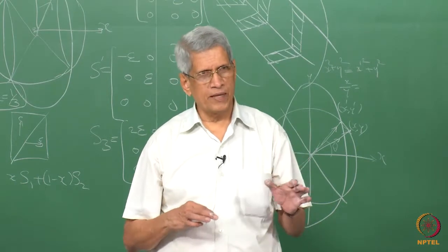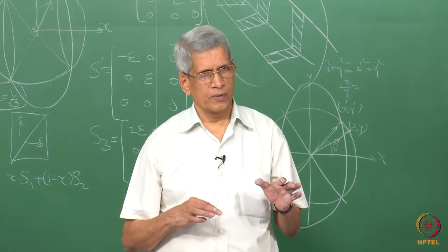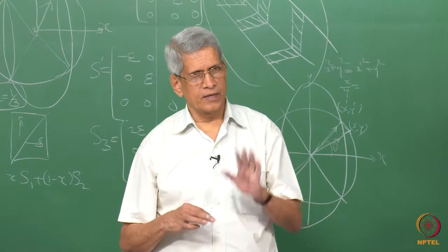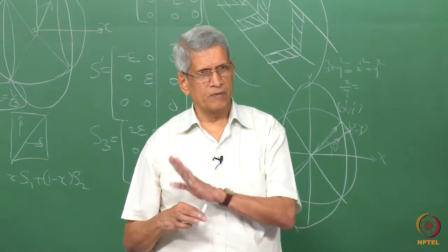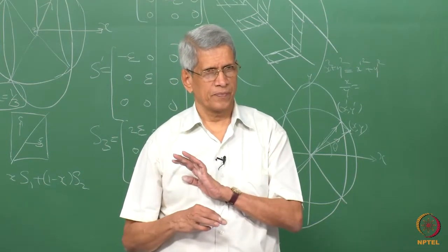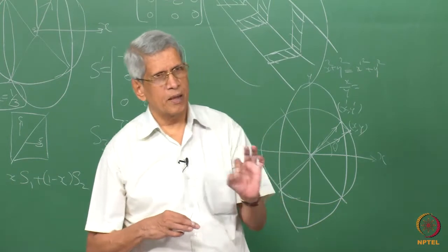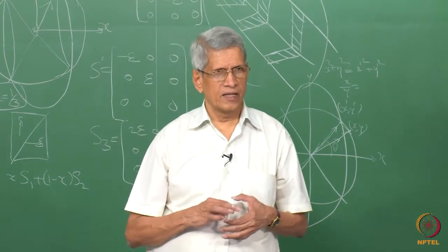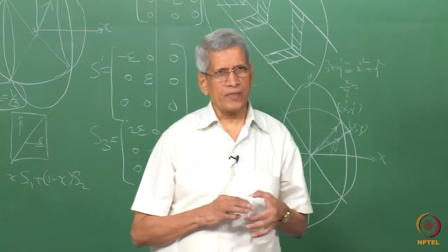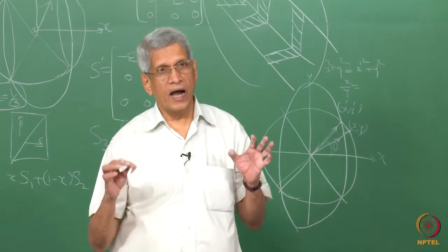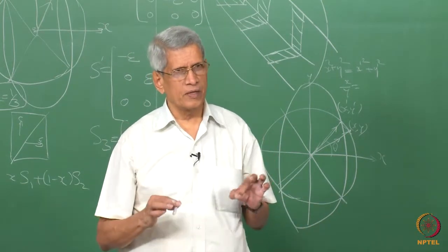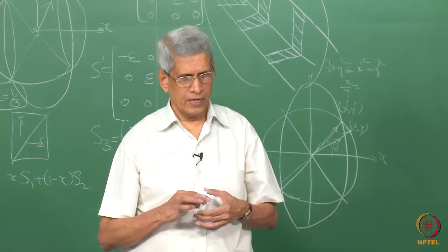Then the habit plane which is calculated turns out to be the same habit plane which is experimentally determined. But we should understand that these habit planes are high index planes, or we call them irrational habit planes.